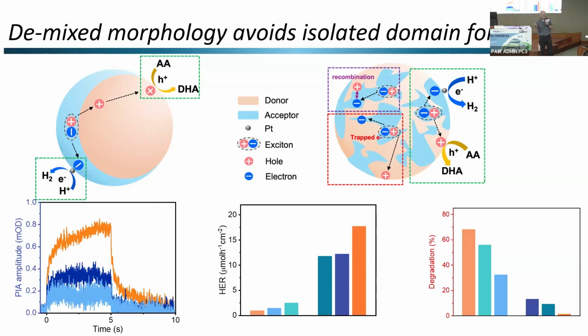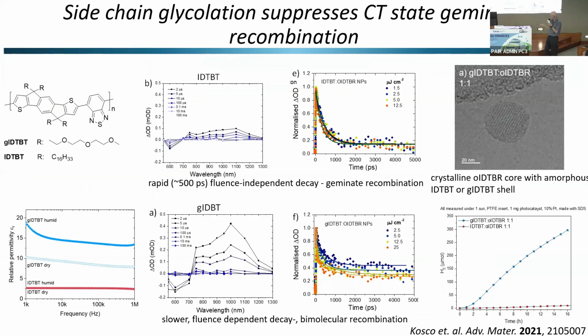So if you generate an excited electron in the middle of your nanoparticle, it's not getting swept to do good chemistry on the surface. It's going to undergo some type of degradation process. And this is well known, particularly for Y6. So we're starting to realize now that we need to have a really nicely demixed system to get almost what I'm calling a broken core-shell. You might also think of it as a Janus-type particle, like 50-50 separated, which looks really quite interesting.